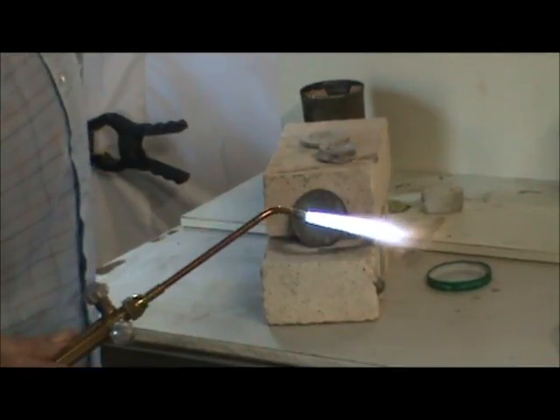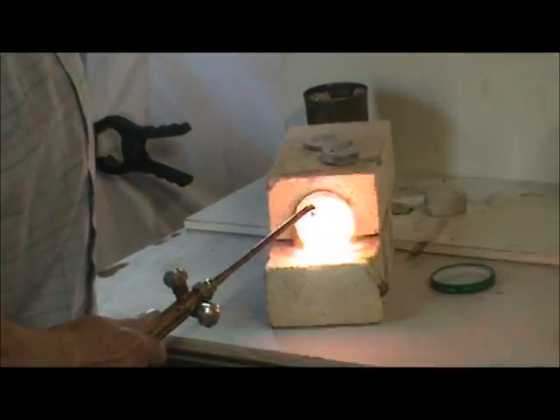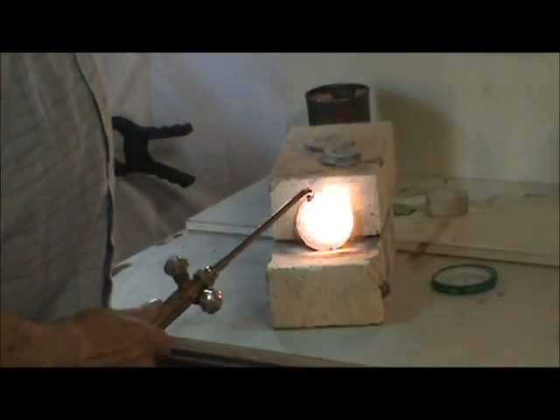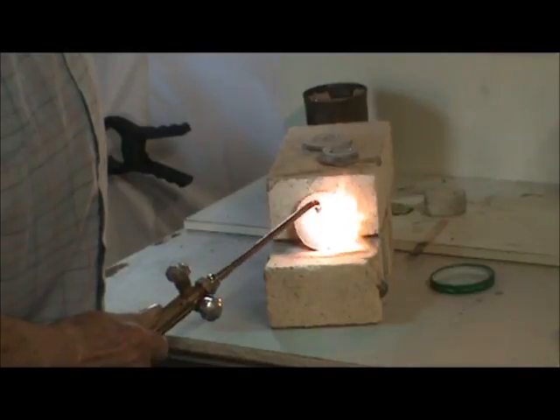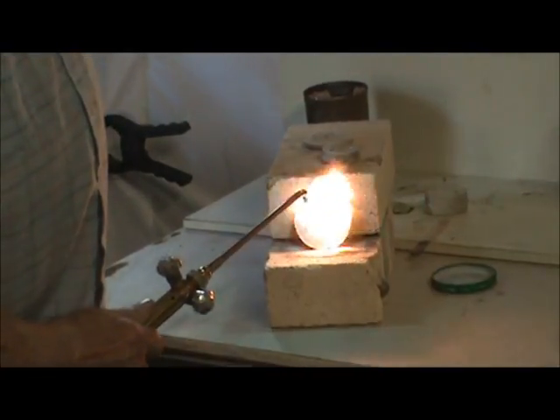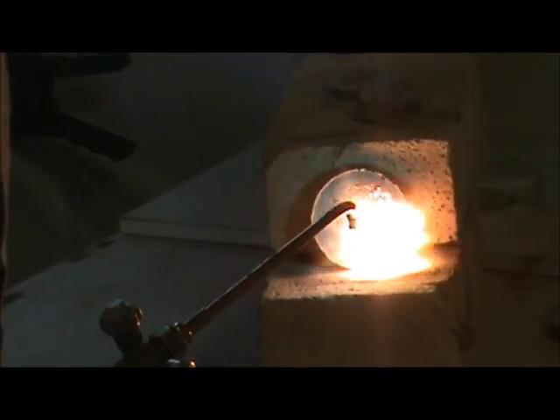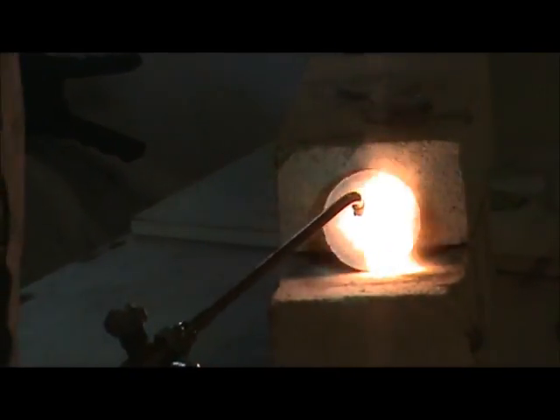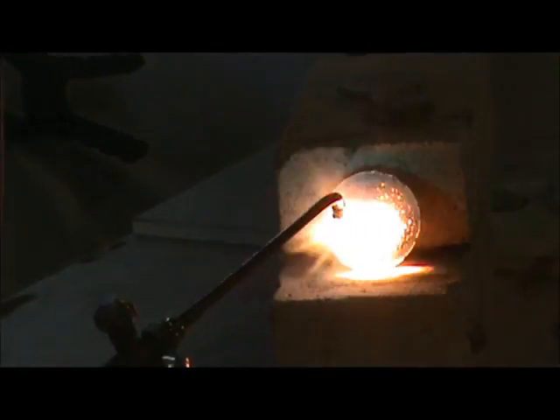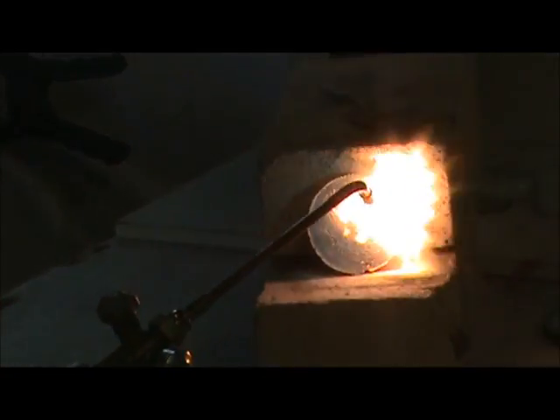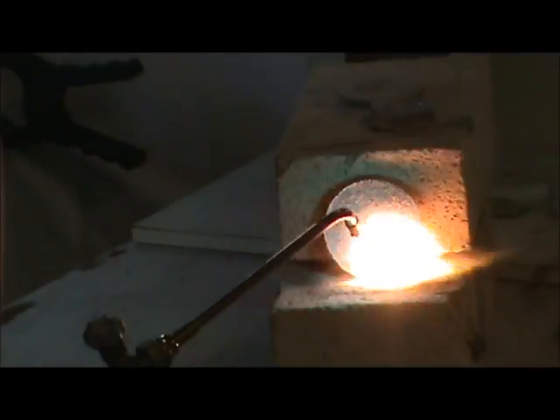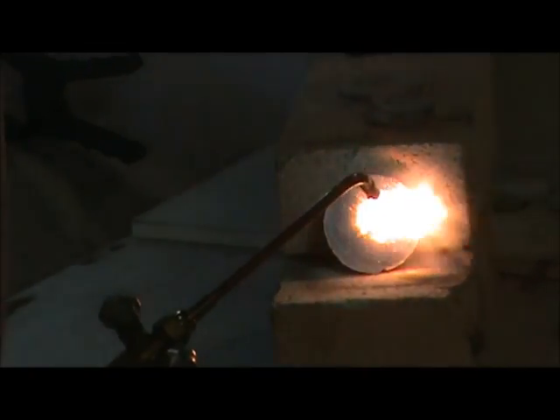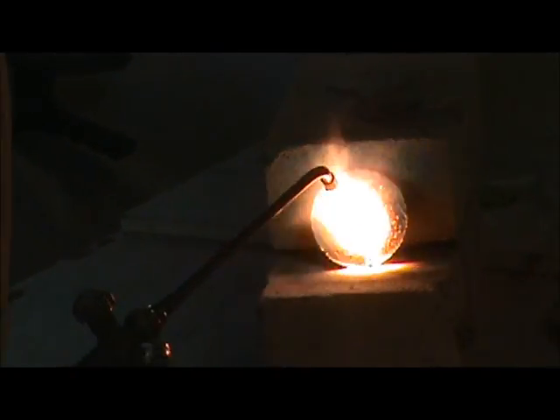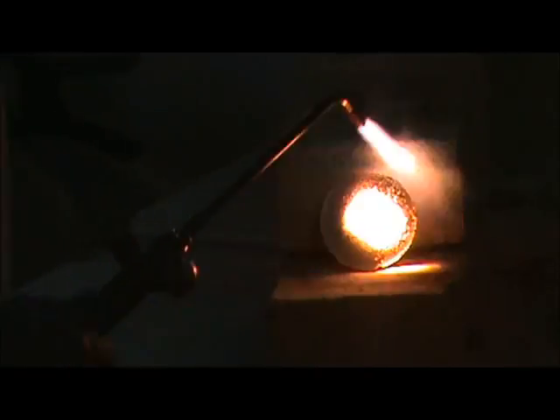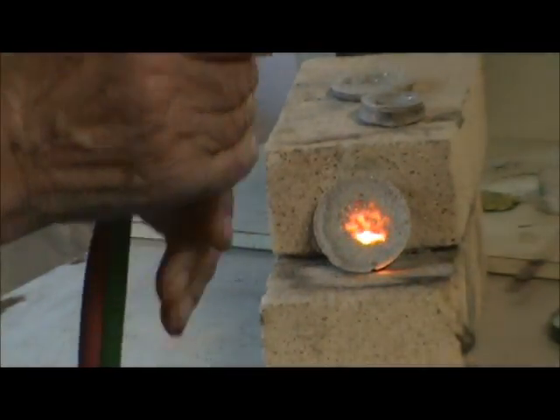So now I'm taking that sample which we just poured a few minutes ago, and I'm heating it with an oxyacetylene torch, and you'll see that to everyone's amazement, the material does not explode as concrete would, or even fly apart, doesn't even crack. We're heating it up, as you can see, to a very high temperature. And it was only poured, remember, about 3 or 4 minutes ago. That was the first sample, the non-boron one.